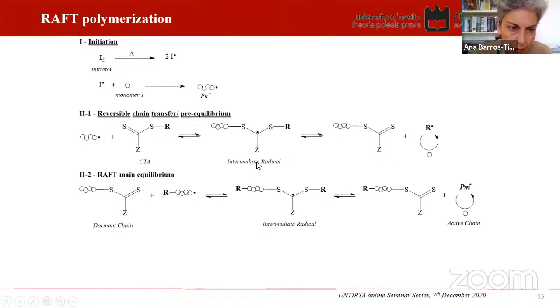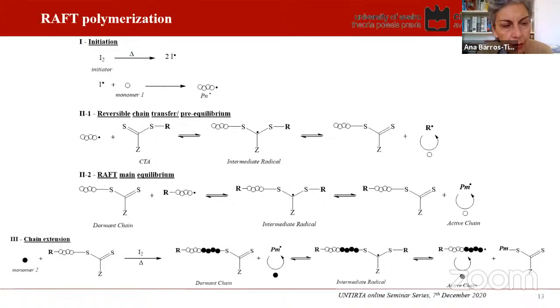So in a larger overview, I'm showing here we have a standard initiation process, which involves an initiator breaking down into two radical species, the initiation step involving this initiator reacting with monomer and starting a growing chain. Then finally, we start the interaction with the RAFT agent. So we have this reversible chain transfer at a sort of pre-equilibrium, where the growing chain is going to transfer its growth to the chain transfer agent, forms this intermediate radical, and then the R group is kicked out. This R group will start another growing chain,